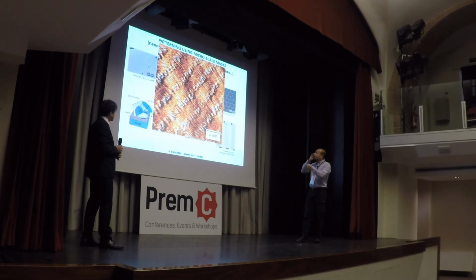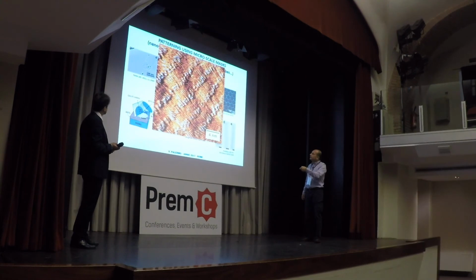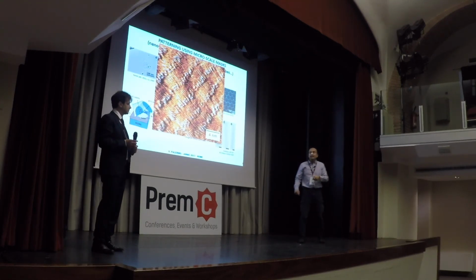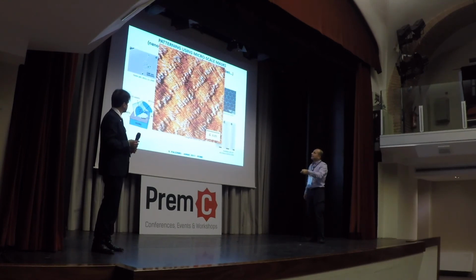So why did we want to do this? Because if you think, here you have alkyl chains that will not perturb graphene that much, but then you have these heads that are charged, and then furthermore they can become reactive and attach to graphene. If this works very well, at the end you have a huge amount of nanoribbons on the whole surface that are created by this kind of self-assembly.